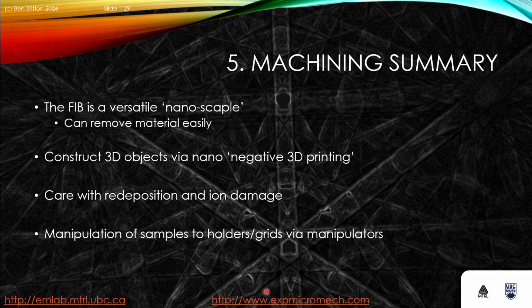So hopefully I've persuaded you in this module that the FIB machining, it's a versatile nanoscalpel. We can effectively remove regions relatively easily, and we can construct a series of three-dimensional objects using negative 3D printing to cut away and create and sculpt artifacts, and specifically for sample prep. In this process, we're going to be very careful with redeposition and ion damage, and we're going to manipulate the samples to hold to grids via manipulators to enable us to have macroscopic objects that are relatively easy to manage outside of the microscope and move between different apparatus.